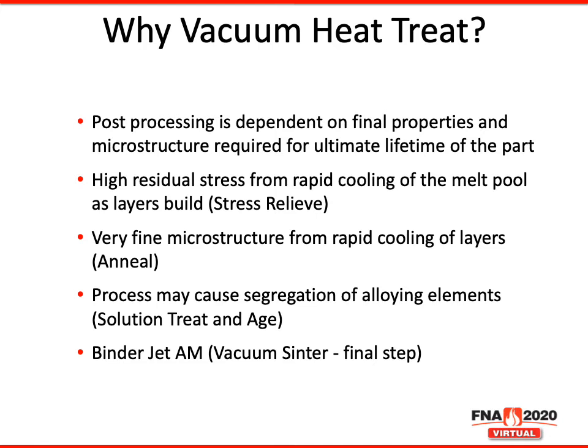So, why do we vacuum heat treat? Post-processing is dependent on final properties and microstructure required for the ultimate lifetime of the part. There is high residual stress from rapid cooling of the melt pool as layers build, which calls for stress relieving of those particular parts. Very fine microstructure from rapid cooling of layers, so we have to anneal. The process may cause segregation of alloying elements, so solution treating and aging. Also, in the binder jet process, vacuum sintering is the final step, which is also important.